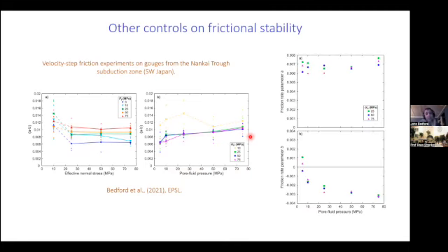And we found that this is actually related to a change in the B value of the rate and state parameter B. The A parameter is relatively constant and independent of pore fluid pressure, but the B values get lower as the pore fluid pressure increases. So I just want to put this slide up to show you that, as well as material properties such as whether the fault's made of clay or quartz, or if it's got heterogeneous distribution, that affects the frictional stability. Also, the other parameters such as the stress conditions, and in particular the pore fluid pressure, also affect your fault stability. And if you want to learn more about that, I would encourage you to go and read that work in EPSL.